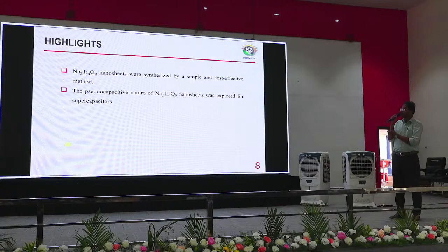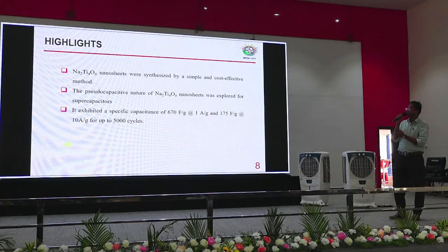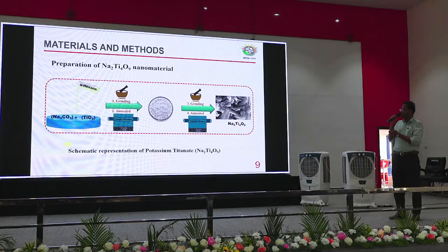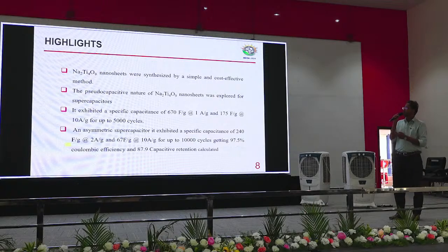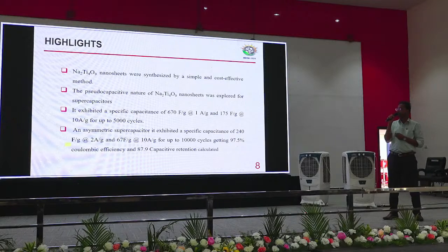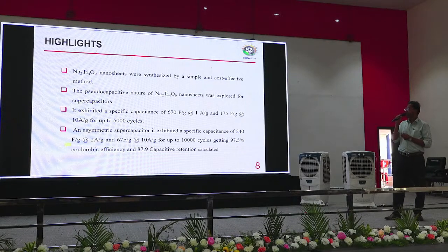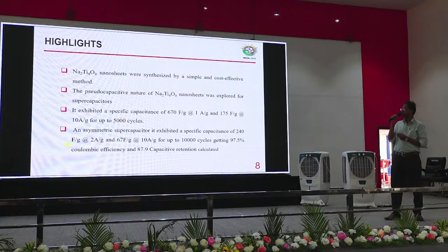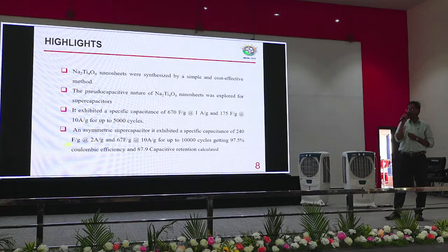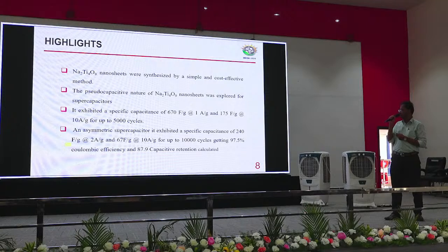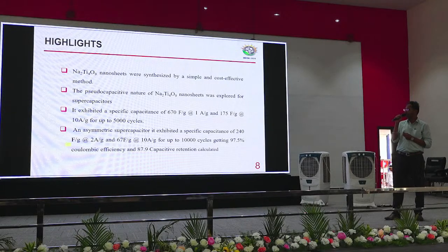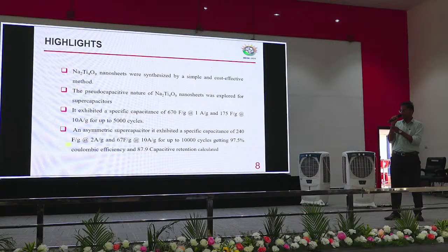First, the highlights of my work. Here, sodium titanium oxide nanosheets were synthesized by a simple, cost effective method. Its pseudocapacitive nature was explored for supercapacitors, and it exhibits a specific capacitance of 670 farad per gram at 1 ampere per gram over around 5000 cycles. We made a two electrode asymmetric supercapacitor device that exhibits 240 farad per gram at 2 ampere per gram over around 10,000 cycles, with good Coulombic efficiency of around 97.5 and 87.9 for capacitance retention calculated.